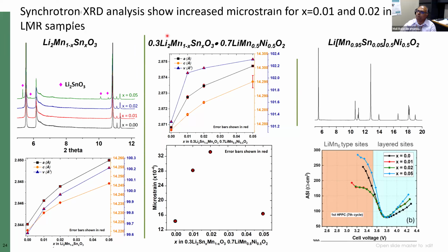And in the case of this composite material, which has both components and is a lithium-rich material, tin can be substituted fairly well. What we notice is that the microstrain increases quite rapidly for small tin dopings, and the microstrain falls down as the doping level increases. So there seems to be some sort of correlation between the strain, the particle size or grain size that one can extract, and the ASI behavior of these samples.